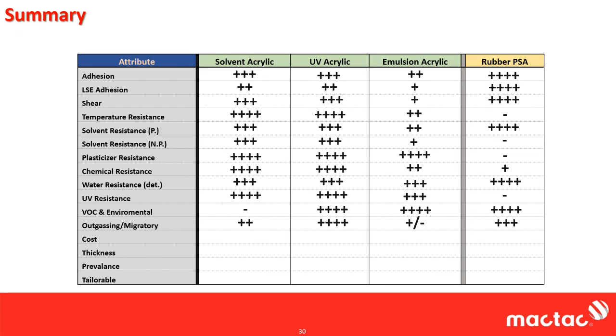It will outgas. And my favorite example of this is Armor All. So you take some Armor All, you spray it on the dashboard of your car, you wipe it in, your dashboard's so nice and shiny, it looks great. 3-4 days, you start to notice a funk on the inside of your windshield. After 2 weeks, the shine of your dashboard's gone and you got this funky film on the inside of your windshield. Well, what happened was all of that material in that Armor All evaporated and condensed on your windshield. So again, it's not considered a VOC, but it is outgassing. And rubber PSAs, they have a little bit of this.